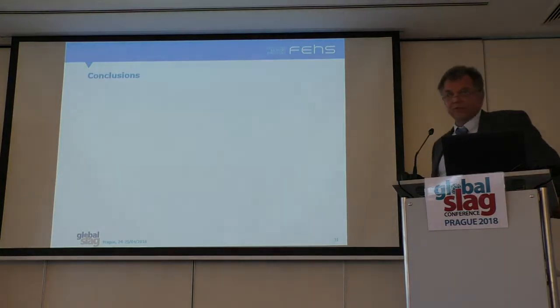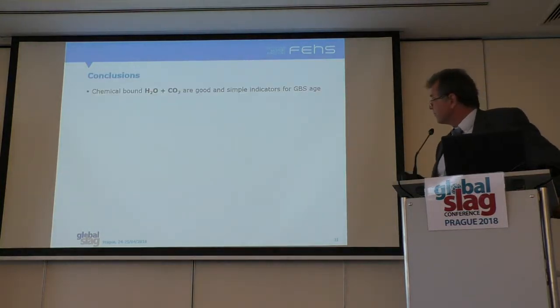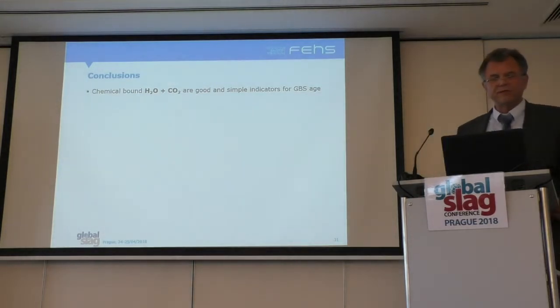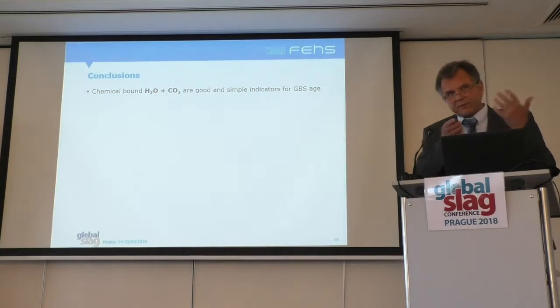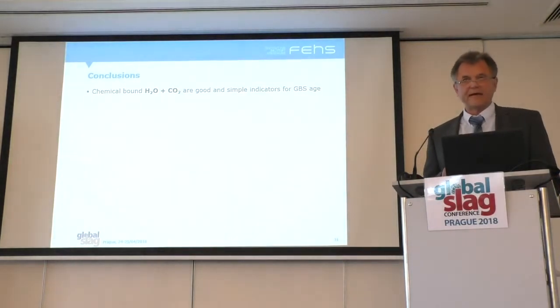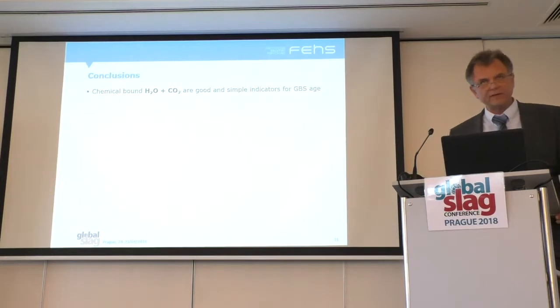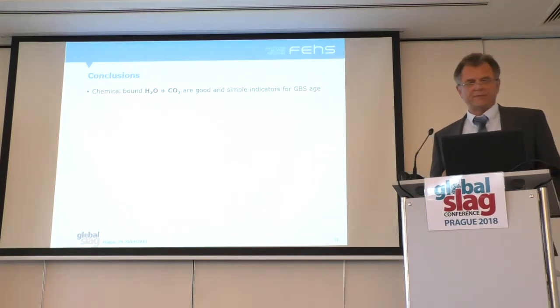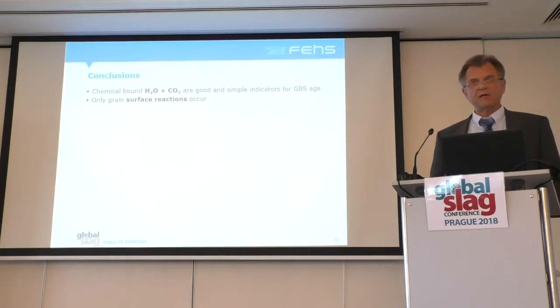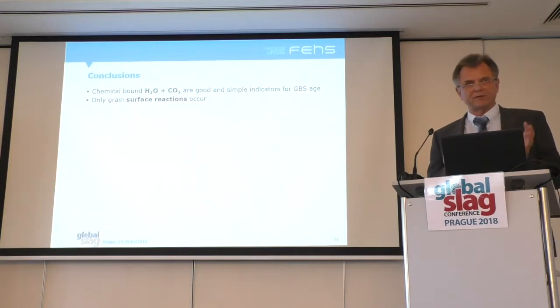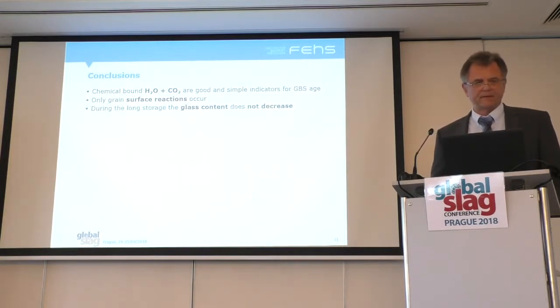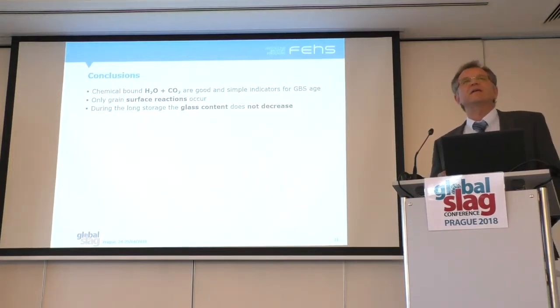Yeah, let's come to the conclusions. Chemical bound CO2 and water are very good and simple indicators to have a first evaluation of an unknown GBS coming from somewhere and stored for an unknown time. We see also after years, many years, there are only surface reactions in micron scale. Glass content will be as high as it was during the beginning of the storing. There is no better grindability.